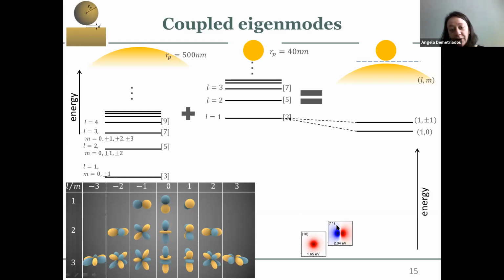And what I'm doing here is plotting the field enhancement in the gap of these 2 modes, also putting them energetically where they should be. So the 1,0 mode, which is shown here, you just see a maximum here in the gap, which is the mode that we usually see and consider in systems like that, and we ignore everything else. There is though another mode, the 1,1 mode or the 1,-1 mode, which looks like this. It has a 0 in the middle, and then it has a plus and a minus on each side.